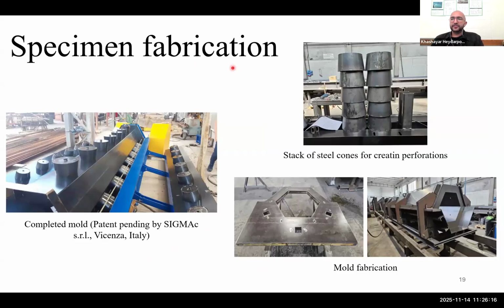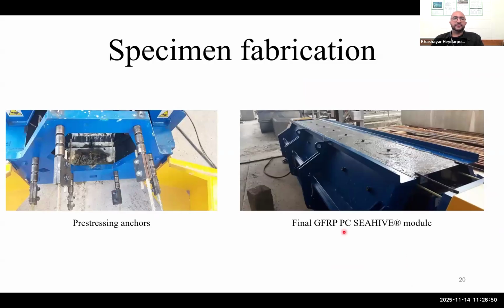Now let's start with the fabrication of pre-stressed SEAHIVEs or PC-SEAHIVE specimens. In the beginning, the steel molds were fabricated, as presented in this image. And the completed mold consisting of the steel hexagonal shape and also the steel cones for creating the perforations was also patented by Sigma C company in Italy. And the GFRP bars were then pre-tensioned using hydraulic jacks and were locked with these anchors as presented in this figure.